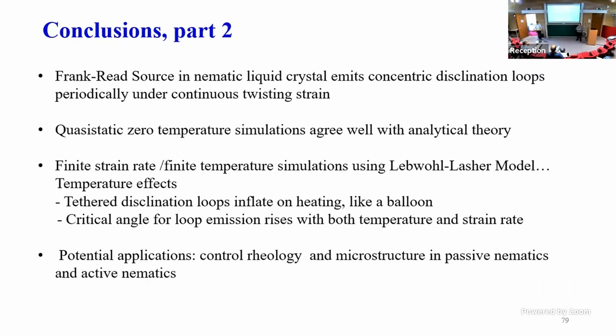So you mentioned having had a couple of these Frank-Read sources. How would the loops interact with each other? Okay. Some of the slides I skipped were from some experiments by Chenhui Peng. He just had a square lattice of plus and minus. What happened is each little half loop went together and annihilated. But that created two loops like this, and then they went together and annihilated. So they were not far enough apart to actually emit loops. They just touched. But if we put those sources far apart, the Burgers vector equivalent for the nematic, well, you can't really define topological charge for the topological defects in a nematic. You can't just give them a Burgers vector. It's more complicated than that. But I think what would happen is that the loops, when they touch, would annihilate and turn into a bigger loop. So essentially you've slipped the region in this loop, you've slipped the region in this loop, so the two slipped regions can merge.